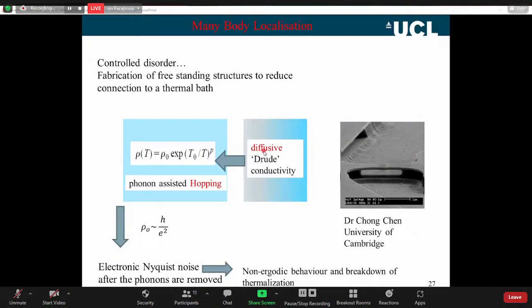And what we would hope to do is to shift from a diffusive conductivity, which is basically the transport mechanisms that I've showed you, into this phonon-assisted hopping regime, which we don't see in the germanium-tin. What we would like to do is to study the effects of many-body localization, where we've taken away the thermal link to a reservoir, and the only noise we've got in the system is a Nyquist noise, so it's kind of an intrinsic electron or hole noise in the system that perhaps drives this activity. And then in such systems, we could study non-ergodic behavior, thermalization, so that really temperature, in a sense, has no meaning because heat can't travel through the system, charge can't travel through the system, but also heat can't travel. That's what we would hope.